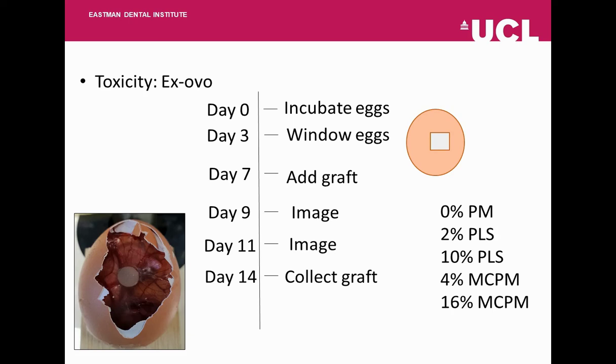Instead of combined formulations, I wanted to see if individually the discs releasing anything will pose any damage or are toxic at all. So I had composite discs with no polylysine and monocalcium phosphate, the lowest level of polylysine at 2%, highest level of polylysine at 10%, and 4% monocalcium phosphate and 16% monocalcium phosphate.